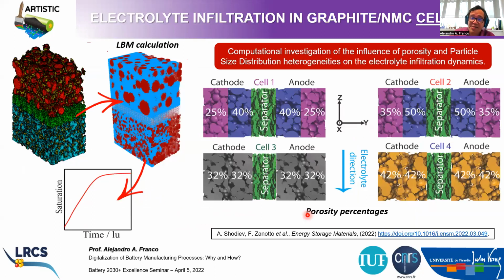This is something that we have extended, actually, yesterday, okay? We published this paper yesterday, which is an extension of this work, where we screen the wettability of different electrode microstructures, right? And here we are playing with the uniformity or heterogeneity of porosity and particle size distribution of active material in anode and cathode. So this is a simulation of the infiltration process now in the full cell, in the sandwich, where you have on one side the anode, on the other side the cathode, and you have the separator, right?